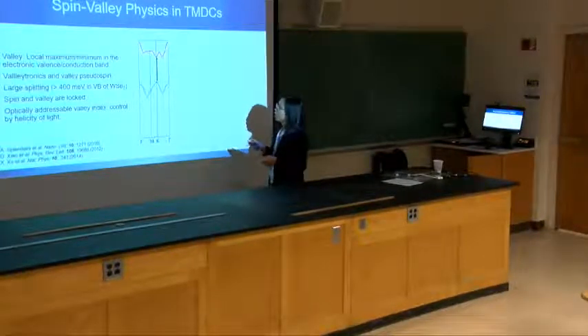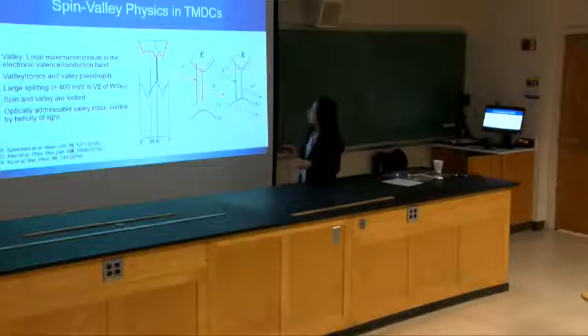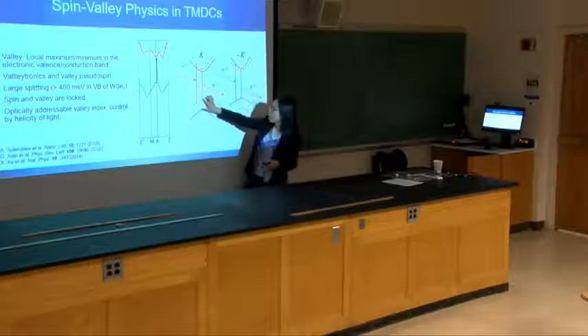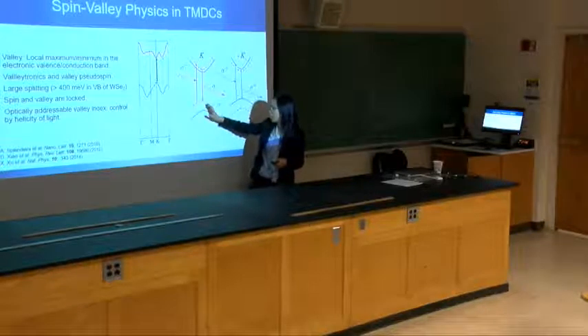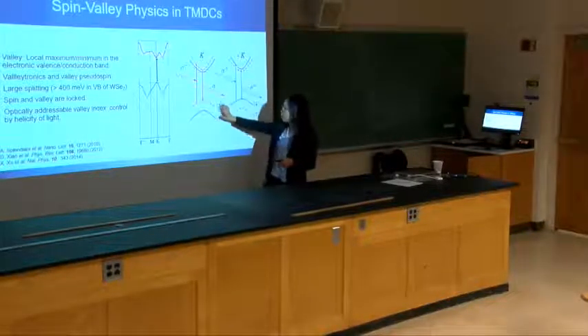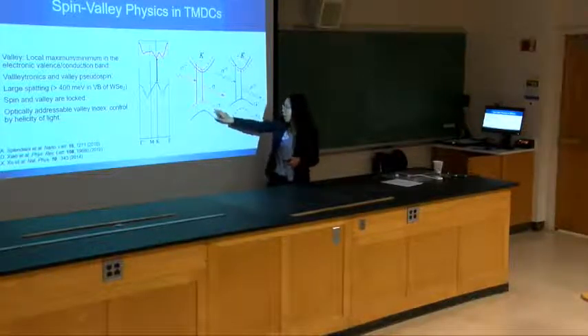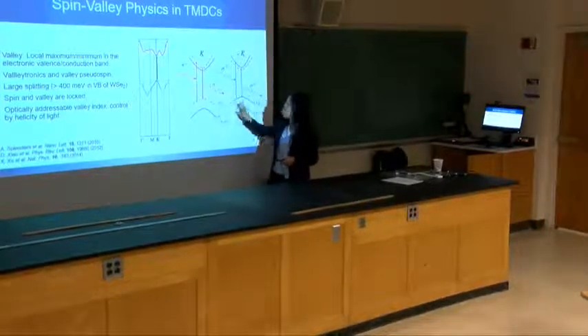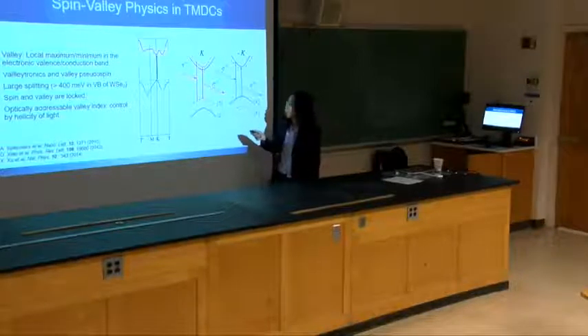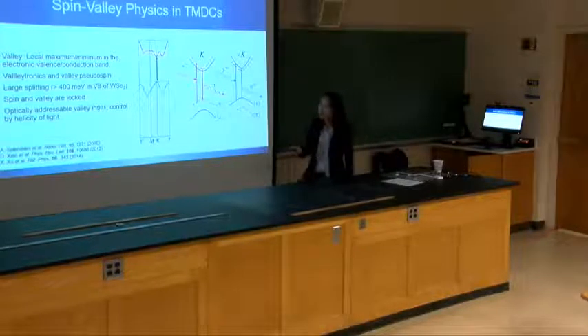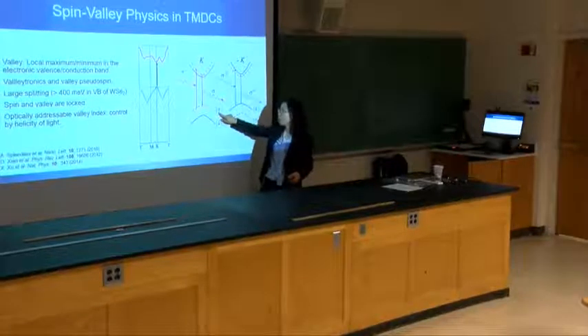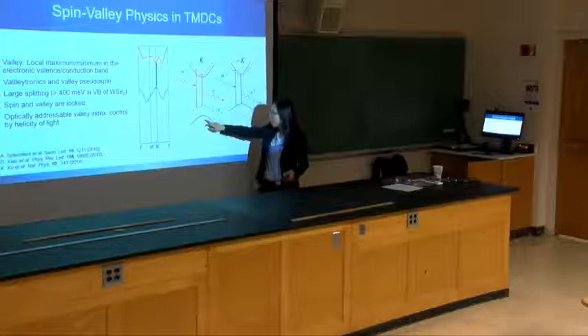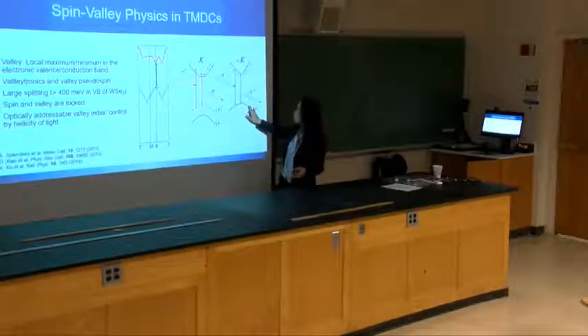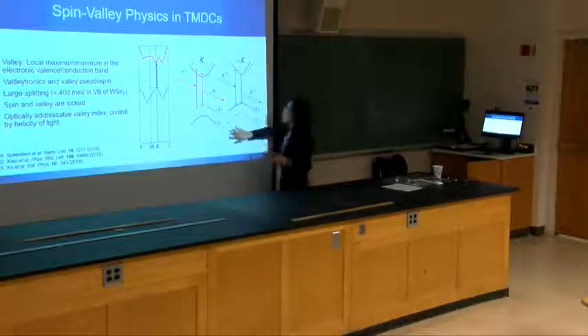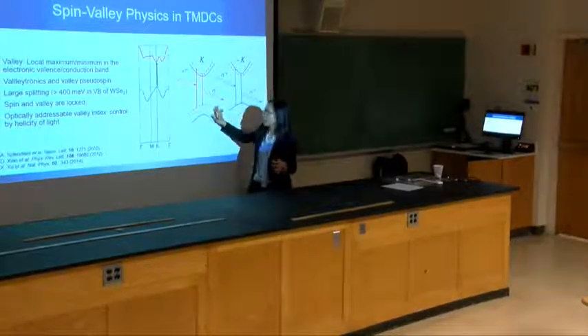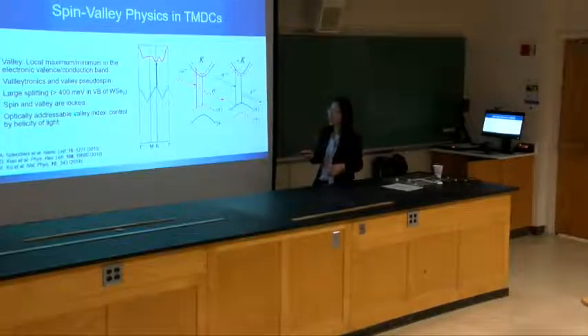If we zoom in on this valley here at the K point, and look at the valence band, first off, we see a large splitting. This splitting is more than 400 milli electron volt in tungsten diselenide. Because of the splitting, these bands have different spins, spin up here, spin down here. Because of time reversal symmetry, if we just look at the valence band maximum, at K point it's spin up, at minus K point it's spin down. The spin valley locking effect means that if we want to flip a spin from spin up to spin down, there are two ways. We can flip it directly, but the splitting is too large, so it's quenched, or flip it to another valley, but the momentum change is too large. This indicates that the valley index is pretty robust. In other words, this is the spin valley locking effect.